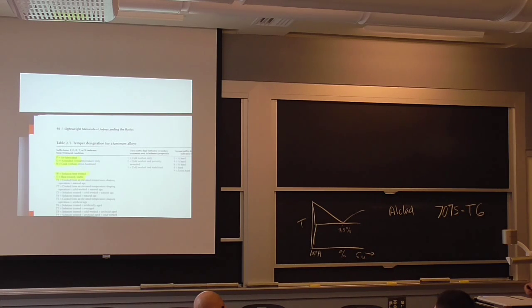H is cold worked. Let's say I get it in the annealed condition and it's 2 inches thick, and I put it through the mill and I go down to 1 inch thick. It's now harder due to the cold work. This is compression, just compression, okay? The grains have gotten smaller. They turned into pancakes from what we call equiaxed. They can become planar type grains, and you get greater strength.